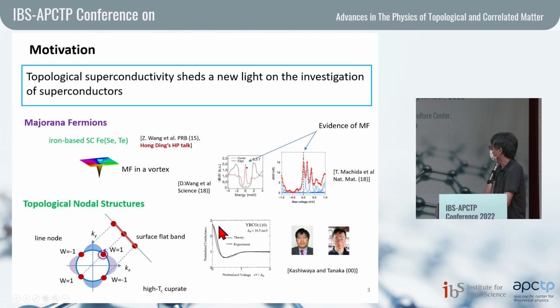Actually, they measured this kind of zero bias structure even before the discovery of the topological insulators. This is data taken by Kashiwaya-san. And as you can see, this data clearly shows the presence of the zero bias peak. The solid line shows the experiment data, and the dotted line shows the theoretical calculation done by Tanaka-san. And as you can see, these two results show a very good agreement. So this should be the evidence of the presence of the surface flat band. So in this sense, we can say that the high Tc cuprate is also a topological superconductor. So we can say that topological superconductivity sheds a new light on the investigation of the superconductors.